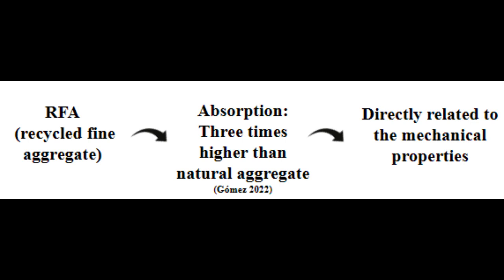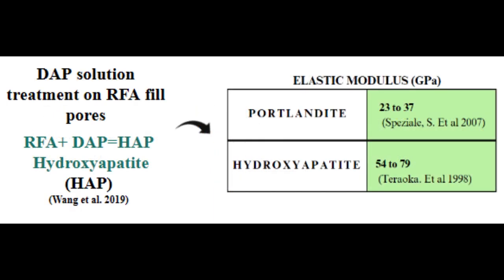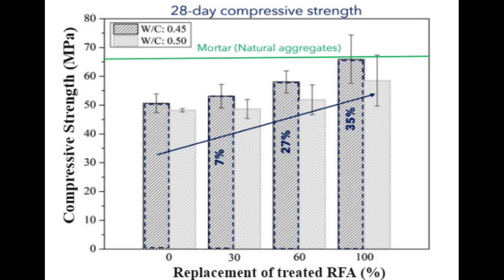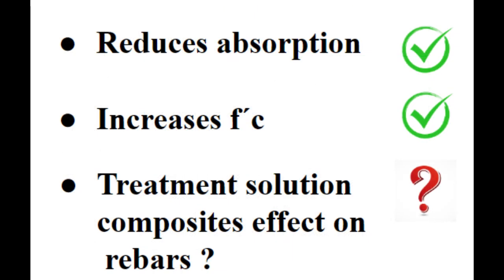To counteract this increased water requirement, the pores of the recycled aggregate must be sealed. Immersing the aggregate in a solution of DAP, that is diammonium phosphate, plus water, has shown significant results in reducing porosity in the aggregate's morphology. This is because portlandite, a form of calcium, reacts with diammonium phosphate, producing hydroxyapatite, sealing the pores, reducing absorption and increasing compressive strength in mortars and concrete, providing optimal conditions for structural use of the aggregate. Following the research line, the effect of treated recycled aggregate on reinforcing steel is being investigated.